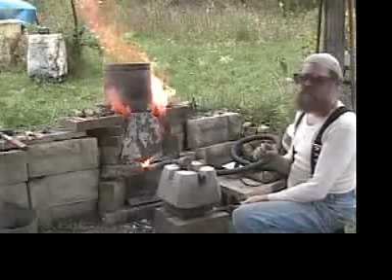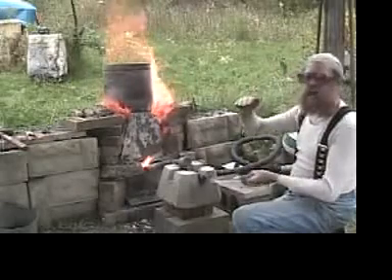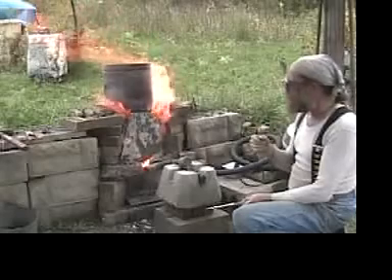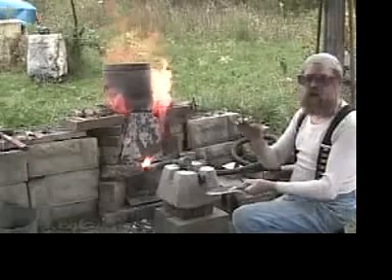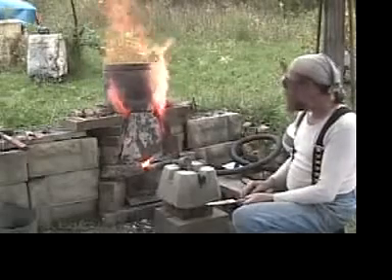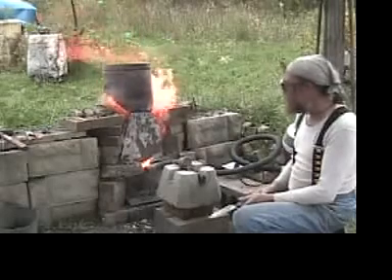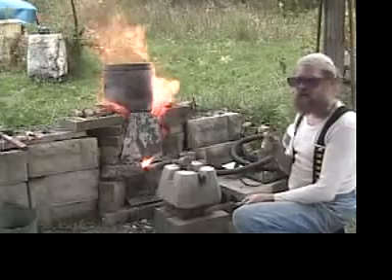It has a smaller particle size. Normally it doesn't take as high a column for that smaller particle to come up to reaction temperature, and because of its proportion of surface area to volume being so high, it reacts quicker. So we're hoping, all put together, we still should be able to get an effective smelt here. Of course, this experiment is about the process, not the product.